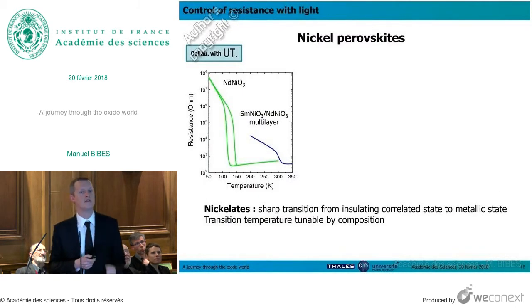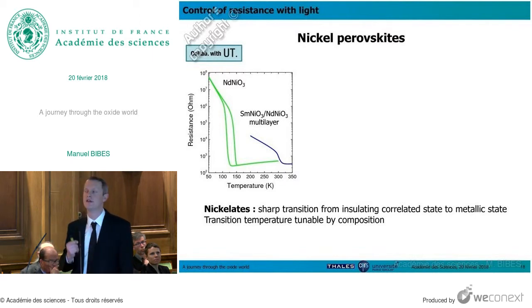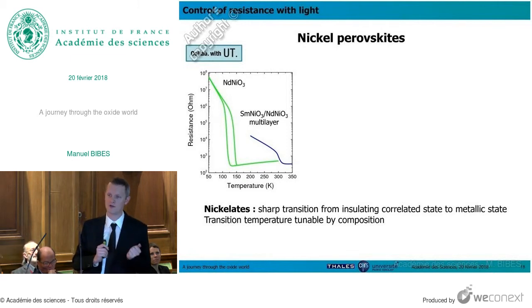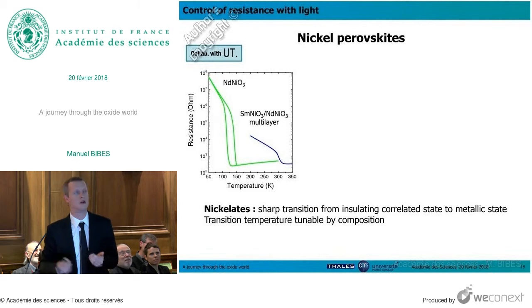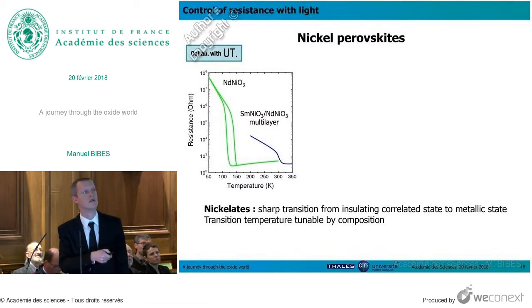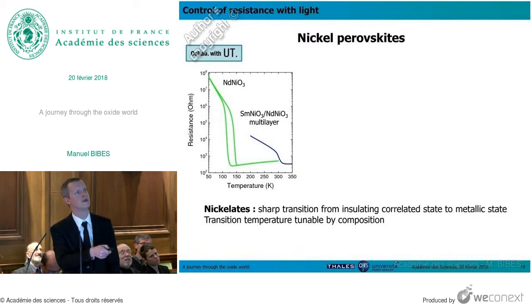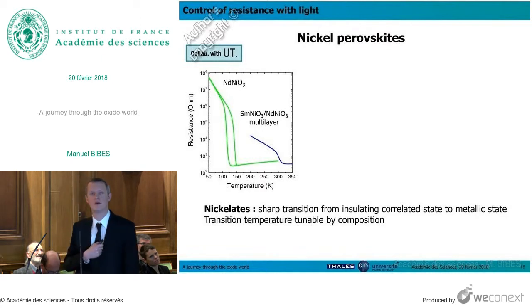So another example is now a charge order material. This is a nickel perovskite. So we have here, for instance, neodymium nickel oxide. And one particularity of this material is that they are very insulating at low temperature and very good metals at room temperature. And there is a very sharp transition between the two states. You see, so that's the resistance as a function of the temperature, very high value at low temperature. This is 50 Kelvin, so more than 200 degrees below minus 200 degrees Celsius. And at room temperature, here you have a low resistance, that's a metal. And so in collaboration again with the colleagues in Twente, we are able to tune this transition to have it just at room temperature, 300 Kelvin.